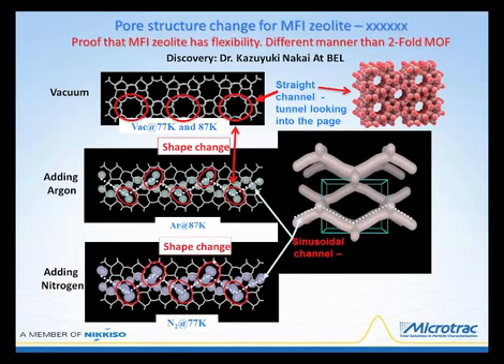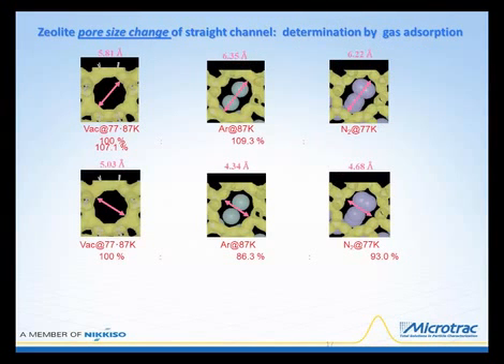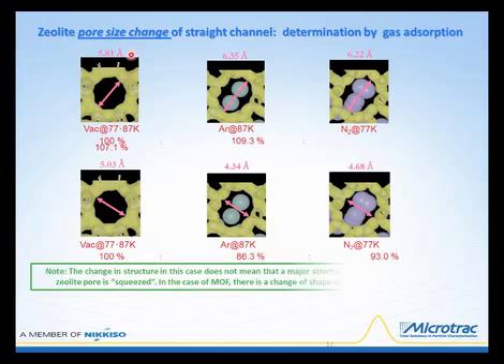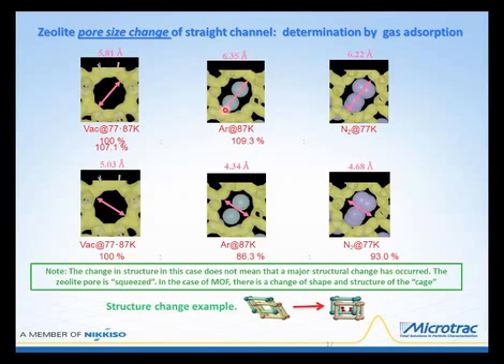But interestingly, if instead of exposing the MFI zeolite to argon we expose it to nitrogen, a further shape change occurs, and this also produces a sinusoidal channel structure. This is the original structure, and you can see it's pretty much circular, and we'd be looking down through this channel. We're going to look at this particular dimension, which is 5.81 angstroms. When we expose it to argon at 87 K, we find that measuring along that same axis, the size has changed to 6.35 angstroms. But then when we expose it to nitrogen, there is a slight change in this dimension, and it decreases to 6.22 angstroms.